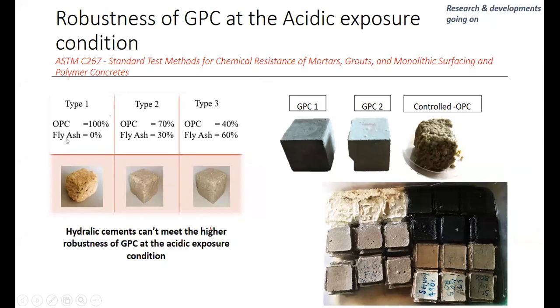So you can see here, this is 100% OPC. This is 70% OPC with 30% fly ash, and 40% OPC with 60% fly ash. You can see the addition of fly ash still delivers better results compared with OPC, but they also have some decay. So here you can see how the conventional concretes perform under acidic HCl conditions; we used HCl for accelerated condition tests. You can see how the new products, which are geopolymers, that we have developed perform under the same condition. The conventional OPC and the geopolymers.